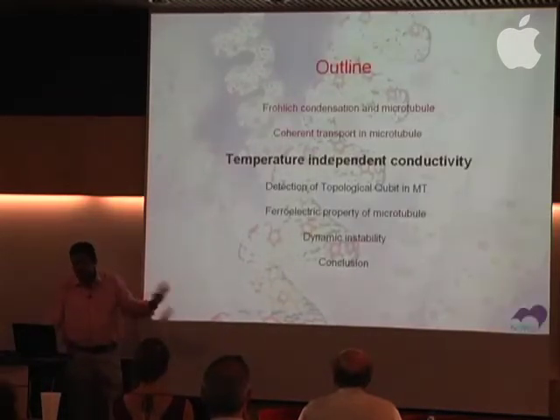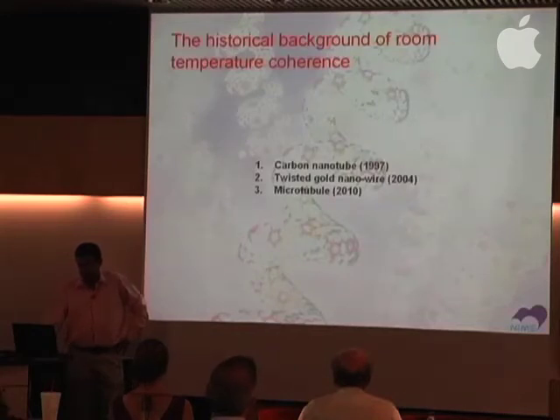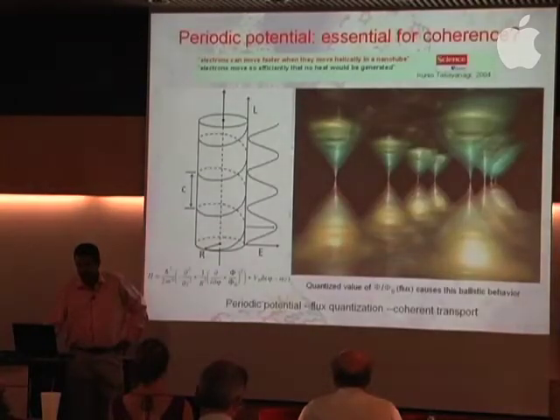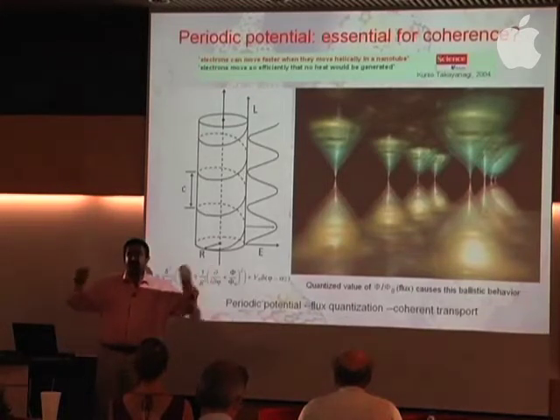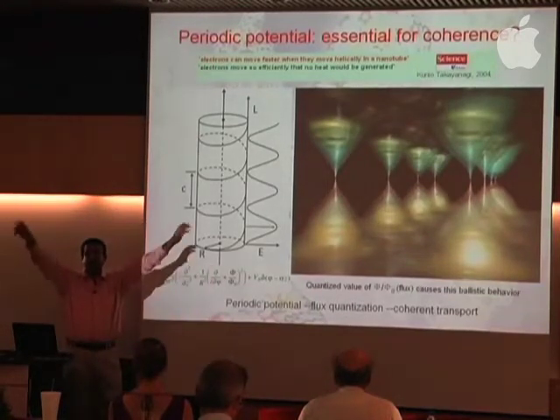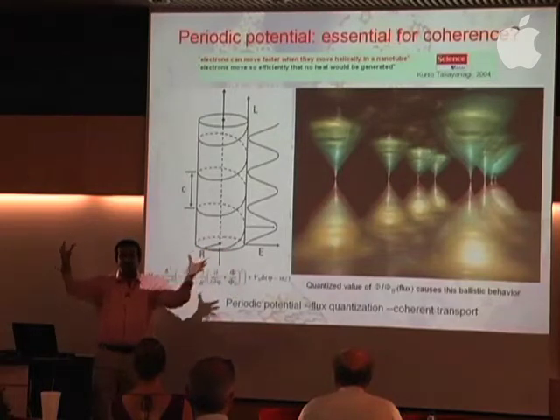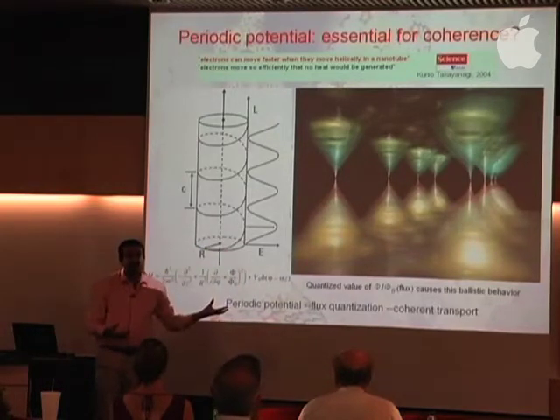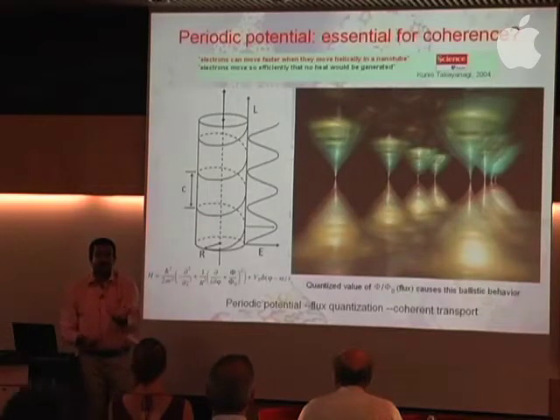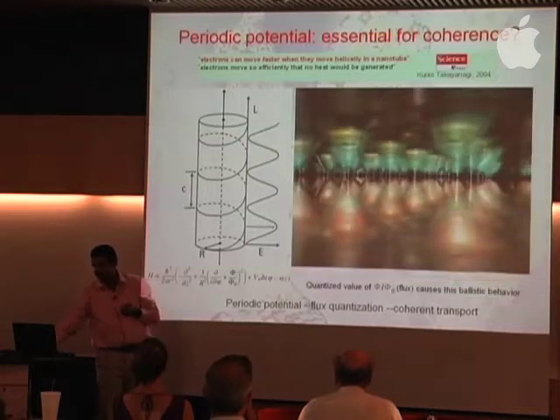Now the most interesting thing of my talk, I consider this the very exciting one: temperature independence. Temperature independence behavior means you change the temperature, and there is no change in conductivity. We have a two-probe setup, we put the entire sample inside a very controlled cryostat system, we change the temperature, and we find that there is no change in the resistance values.